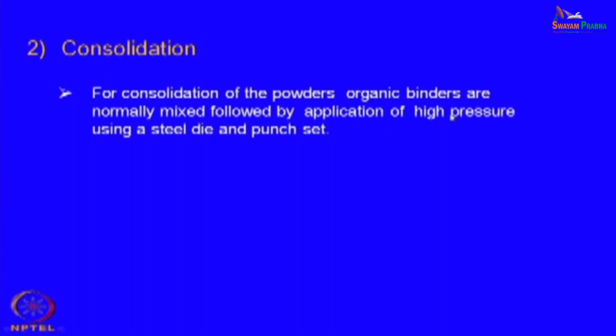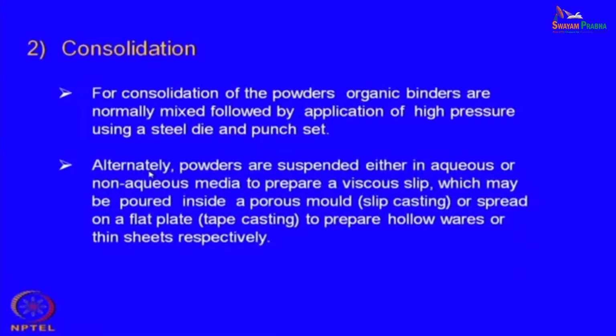In green ceramics, the powder cannot be loose, they have to adhere to each other, and therefore, to facilitate that you add some organic binders. They are mixed, followed by application of high pressure using a steel die and punch. Depending on the shape and size you need, you have a steel die and punch or a mold in which these powders are compressed under high pressure. Depending on the size, shape and the quality of the product you make, at times you have to apply thousands of tons of pressure or load to consolidate them. So, this is one of the simplest ways to consolidate the powders or give a shape to the powders.